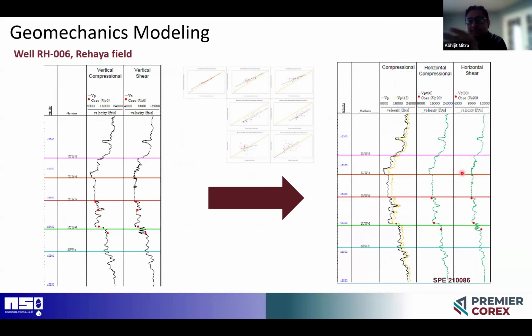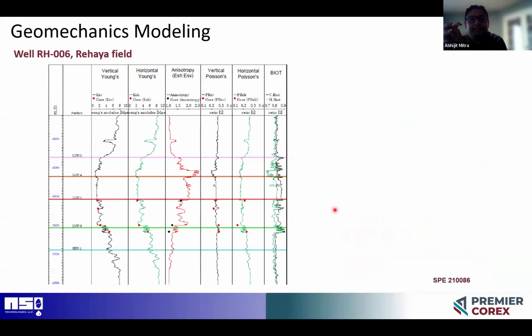And then once we have everything, if you go to next, we can generate these static anisotropic mechanical properties like the vertical and the horizontal Young's modulus and Poisson ratio, using well-published rock physics equations. And finally, we also measure the Biot poroelastic coefficient, and we can have this sort of pseudolog for the Biot coefficient as well. And it always helps to have something like offset data or things like that. But if we don't have it, we still have some internal checks or validation exercises to run.